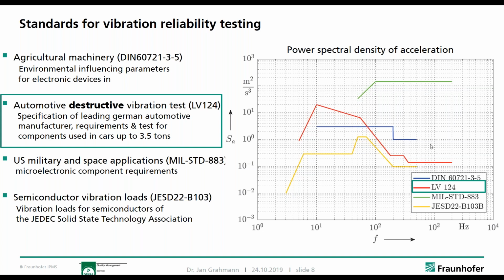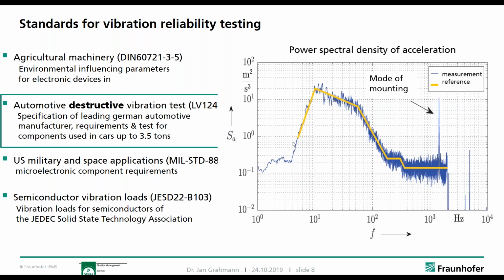So we calibrated our measurement setup, and what you see here is the reference of that standard I just showed you in yellow, and the blue line is the actual measurement by an acceleration sensor of the power spectral density we applied to the devices. And there you have, of course, a certain noise. The mode back here has nothing to do with scanners, because here we did not even use a scanner on the setup yet. That is a mounting mode of the setup we use to put the scanners onto the vibration setup. Okay, and again, you see here the highest load is between 3 hertz and 200 hertz, because here you have the highest power spectral density for the devices.